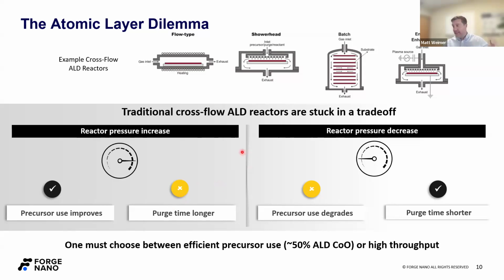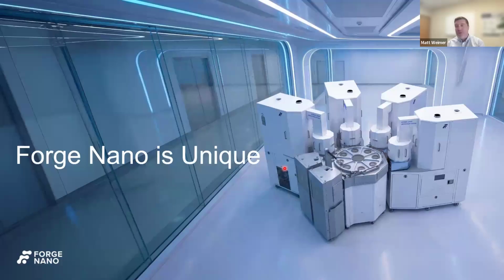So a lot of people said, all right, let's go to low pressure. This is how 300 millimeter silicon tools work. And it works. You do have shorter purge times, but you find out that you have to put a lot more precursor in to get that uniform film that's required. So the amount of purge time that you are reducing is not as much as you would actually calculate. So, you still aren't really breaking that trade-off. And so that's a good segue into why what we do is unique.